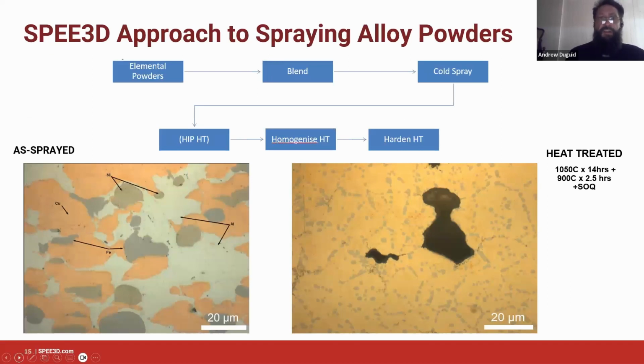Okay, so what does that look like? As a process, you can see it mapped out there. We start out with elemental powders, is what we landed on. We blend those, we cold spray them. We do some heat treatments, winding up with a hardened alloy at the end of that. The critical thing to look at here is this homogenization process. If you look at the micro on the left there, that's our as-sprayed material. And as you would expect, you can literally discern each of the different alloy constituents as elemental powders in that microstructure.